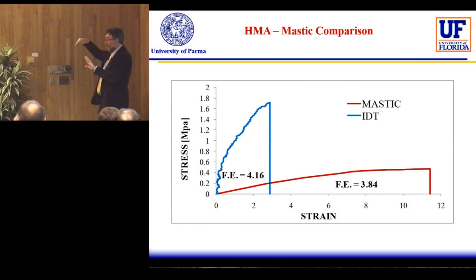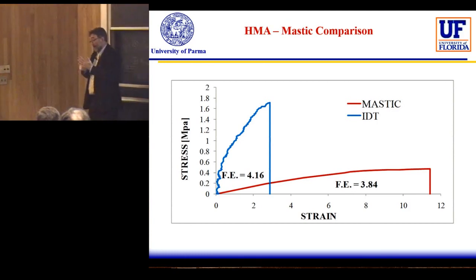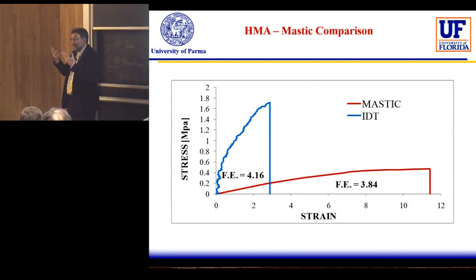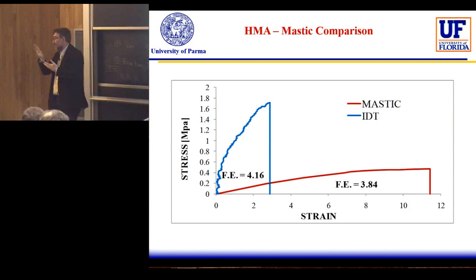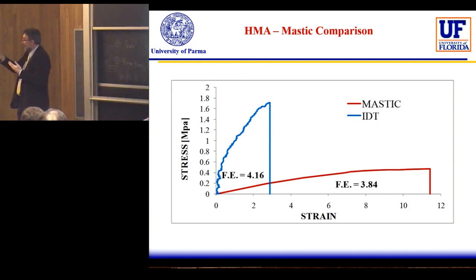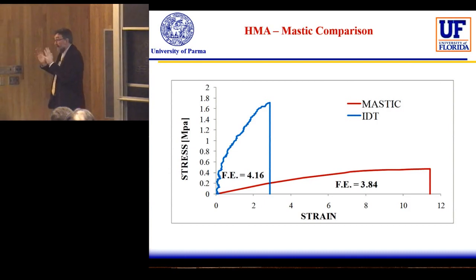If you have bitumen, when the volatile part goes out, you have a material that becomes stiffer, more brittle. A change in that behavior was observed, and the hypothesis was that the lime works as a sponge and attracts the bitumen inside and delays the volatilization of that. Another explanation is that the surface of the different materials can be different and can interact in a different way with this heterogeneous material, having some kind of physicochemical reaction. Those are the hypotheses behind that.